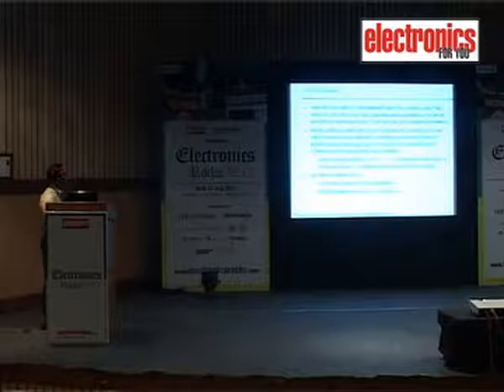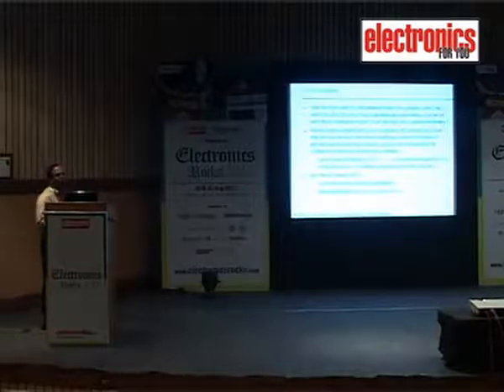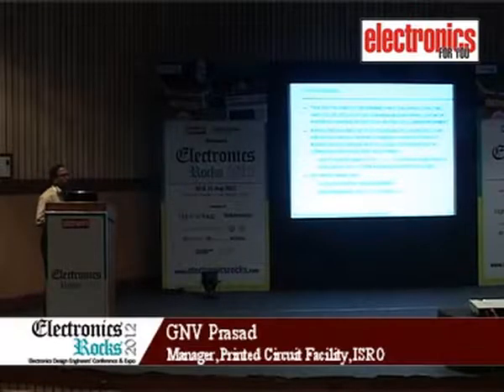Then, one of the important things for the performance of the spacecraft is that the PCB used in a spacecraft should not degas too much. There is a limit. We have a TML, that is total mass loss, which should be less than 1%, and we have to have a CVCM of less than 0.1%. These are the requirements specified for space applications. Because a lot of organic things we use in manufacturing these PCBs will start emanating gas. These will condense on the optics of the spacecraft, which can affect the total performance. Though your electronics becomes highly reliable, your optics gets covered with these gases, and the whole spacecraft fails due to this.